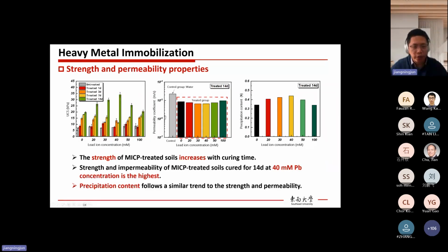Then for permeability coefficient, we find the same thing. The lowest permeability coefficient happens when the lead concentration is 40 millimole. So that's very interesting. It's not 0, but it's 40. Then we measure the precipitation content. We find that for the 40 millimole case, we have the most precipitation content, more than 0.4%. Not too much, but we have the most here.